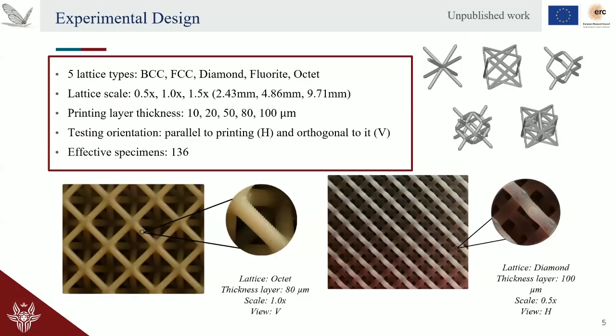Here is the design of experiment used in this work. It's very simple. It's based on a standard hypercube. I have considered 5 different types of lattice cells. This is a preliminary study, so this will be expanded in the future. We have the most common ones: the BCC, FCC, diamond, fluorite, and octet. 3 different lattice cell sizes, and 5 different printing layer thicknesses, because we are dealing with SLA printing, ranging from 10 microns to 100 microns, and 2 different printing orientations, both in axis with the printing direction and orthogonal, for a grand total of 136 specimens.